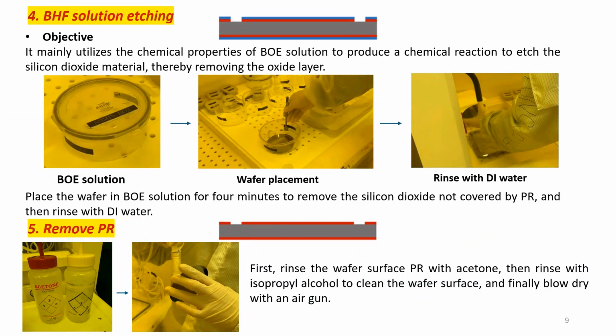Then BOE etching is performed, which mainly uses the chemical property of the BOE solution to etch the silicon dioxide material. It will remove the exposed oxide layer. The specific step is to place the wafer in BOE solution for 4 minutes to remove the silicon dioxide not covered by PR, and then rinse with DI water. To prevent the PR from affecting the TMAH etching process, first rinse the wafer surface PR with acetone, then rinse with IPA alcohol to clean the wafer surface, and finally blow dry with an air gun.